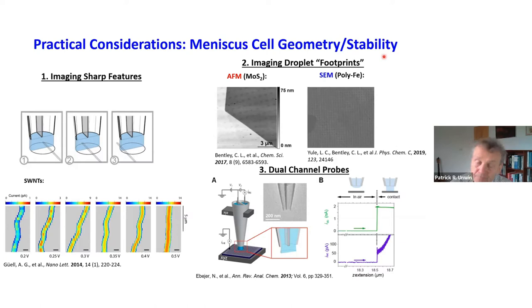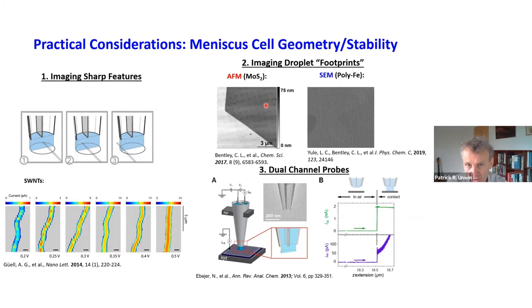To assess the meniscus cell size and stability, the simplest approach is to visualize it. In hopping mode, we land the meniscus on a surface, pull it away, and move to another spot. We can then go back and analyze the meniscus residues with AFM or SEM, and you can see beautiful uniform footprints on the surface.